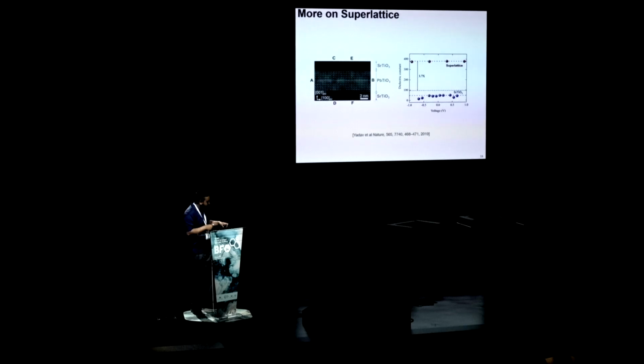So in that continuation, one of the experiments that I thought, when we did this, would be my end with negative capacitance is an atomistic imaging of the effect. So this is a superlattice. This is STO, lead titanate ferroelectric, and STO. And this is done with my colleague at that time, Ramamoorthy Ramesh, whose group actually grew these materials. And what we could do, by looking in the TEM, is map out the polarization in this system. So you can see the polarization unit cell by unit cell here, because you are looking at the deflections of the atoms unit cell by unit cell.